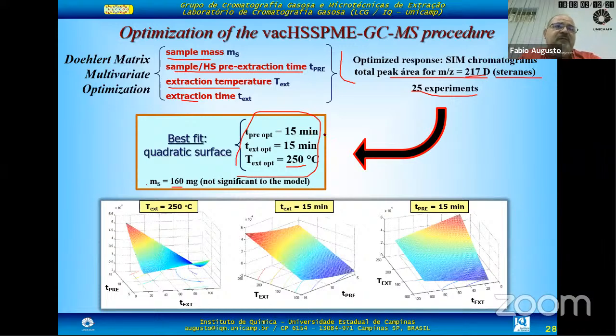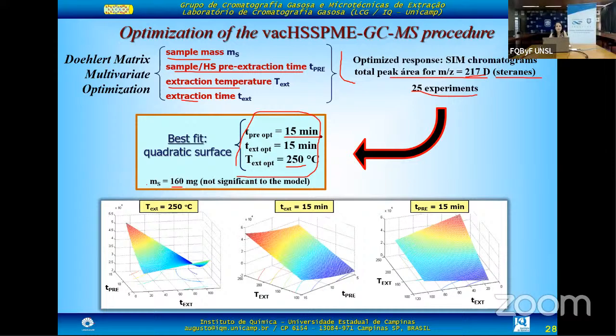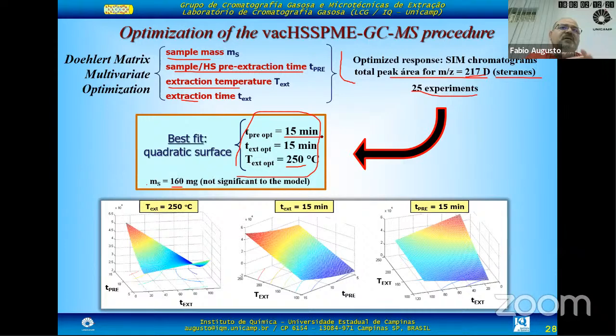And after evacuating the vial, what we found is that in 15 minutes of pre-extraction equilibration, we reached the maximum extraction efficiency. So 15 minutes equilibration under vacuum, 15 minutes extraction was okay here. To go from atmospheric pressure to the operational pressure, in 2 or 3 minutes we reached that pressure with this pump. I believe that other more sophisticated pumps would be more efficient than that, but that was okay. Nothing bothered us that implied more operational time and slower analysis. Thank you, Fabio.